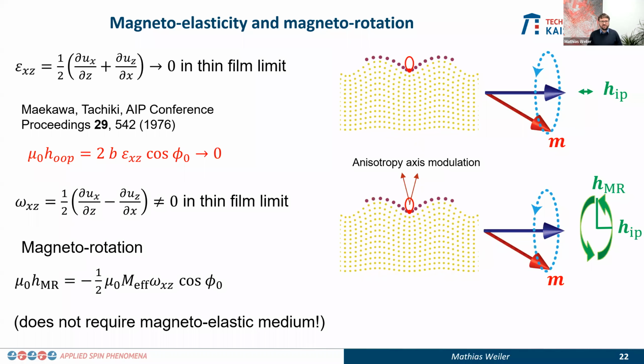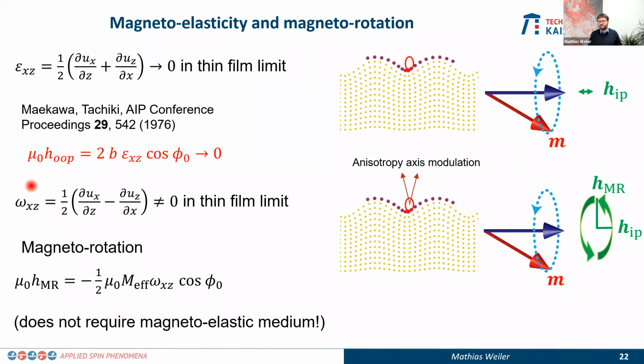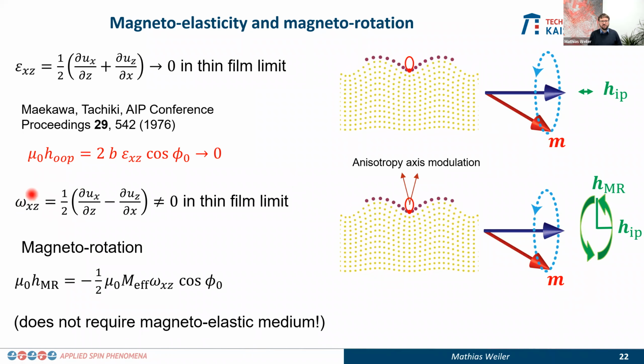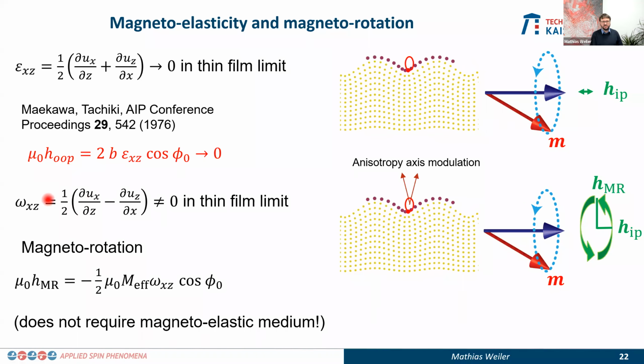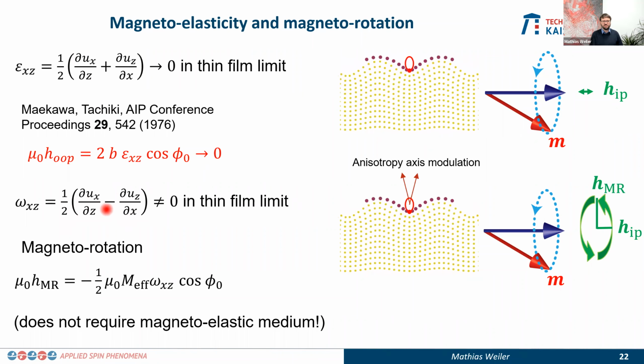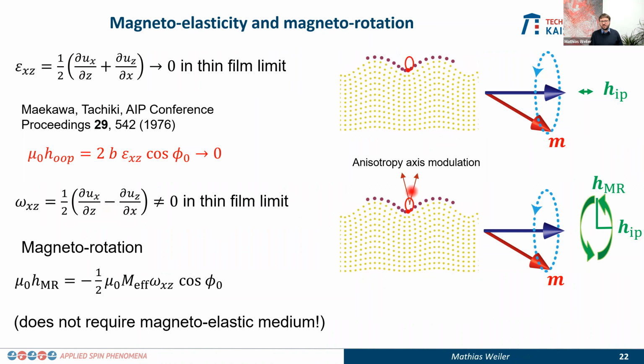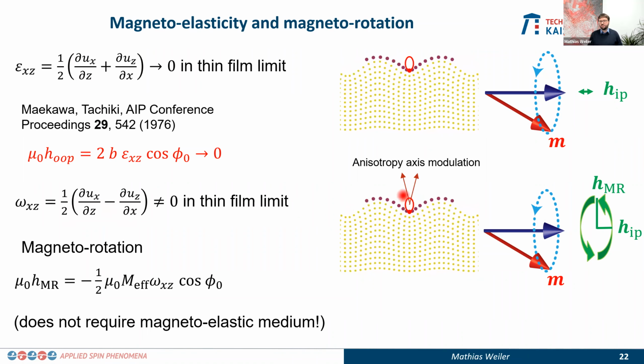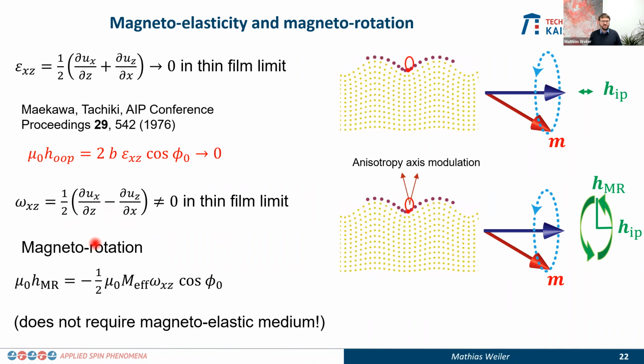However, what comes to the rescue here is the so-called magneto-rotation. Okay? And the magneto-rotation is really directly this rotation motion of the individual lattice atoms. That gives a rotation that is described here. So the only difference to the shear strain is the sign here, so it goes from plus to minus. And this rotation also exists at the surface, or it is even maximized at the surface.